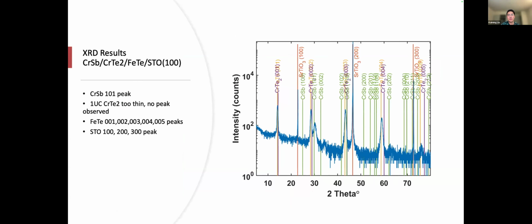And the XRD results show the chromium antimony 101 peak, and 1 unit cell of chromium ditelluride remains too thin to detect, and iron telluride shows the expected peaks. So the chromium antimony peak confirms its growth, but combined with the AFM topography, it is not ideal, and the phase is different.